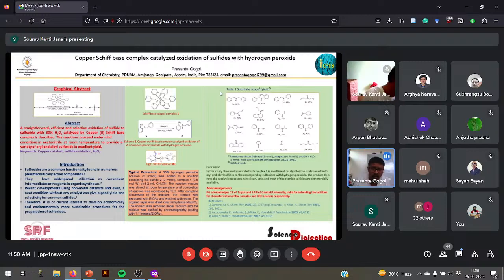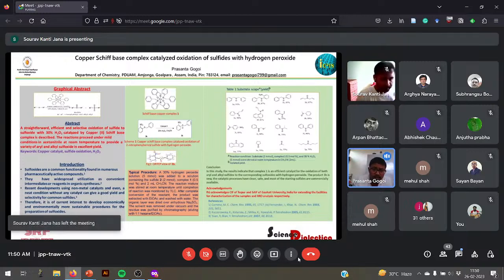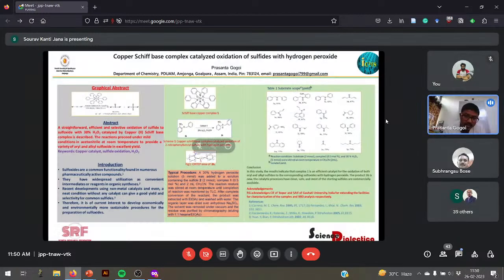Here, the sulfoxides are common functionality found in numerous pharmaceutically active compounds. They have widespread utilization as convenient intermediates or reagents in organic synthesis. In recent developments, using non-metal catalyst and even a neat condition without a catalyst can give a good yield and be selective for common sulfides. But the main difficulty in earlier methods is that many methods could not oxidize the varieties of sulfides. Therefore, it is of current interest to develop an economically and environmentally more sustainable procedure for the preparation of various sulfoxides. So in the present method we use a copper Schiff-base complex to oxidize the sulfide.